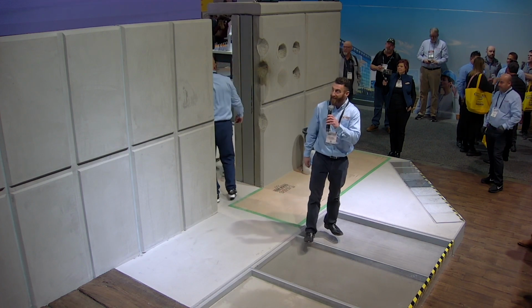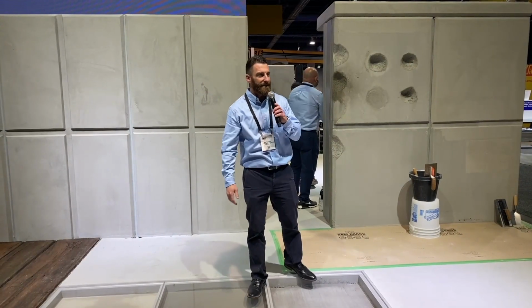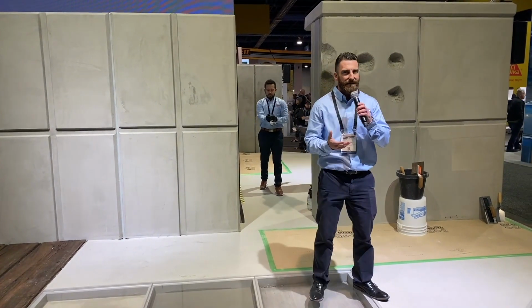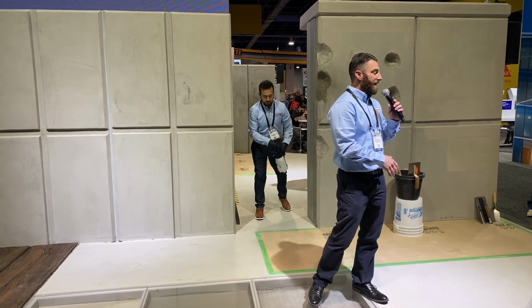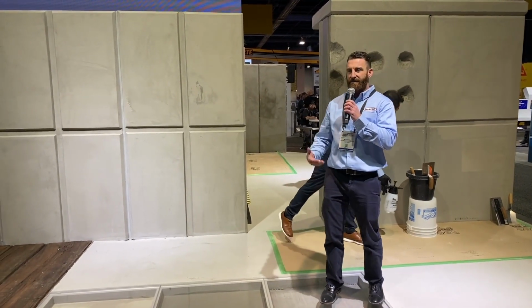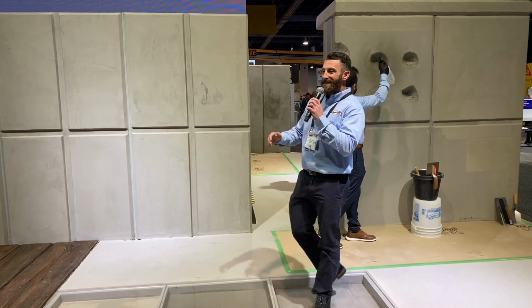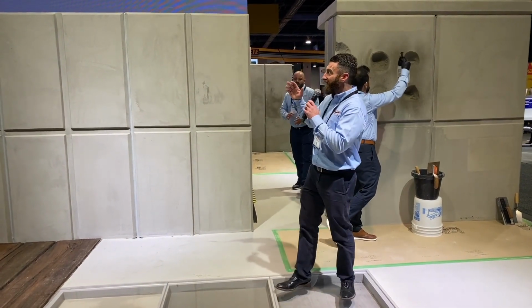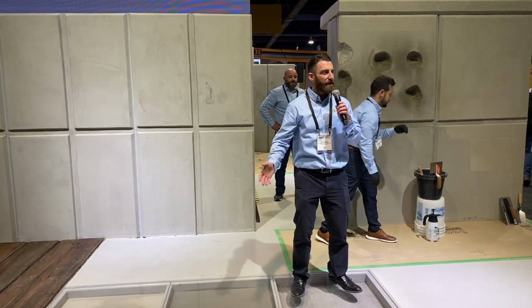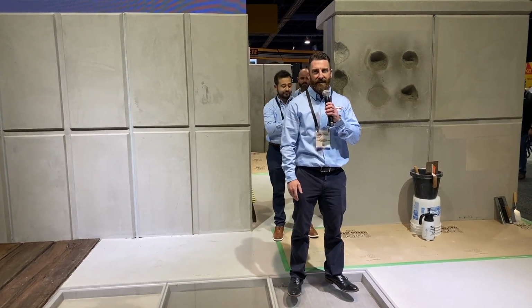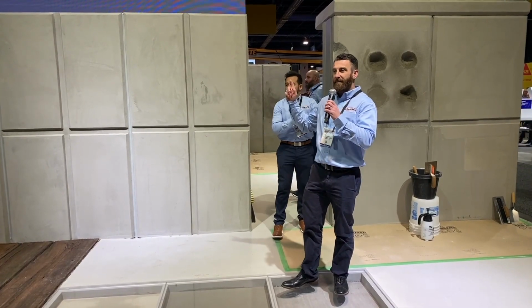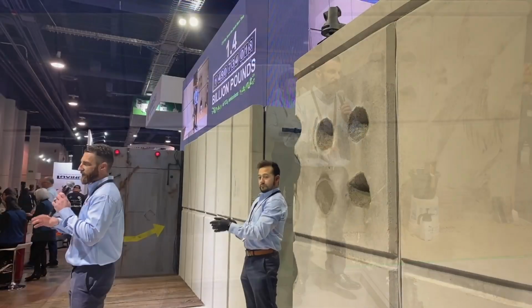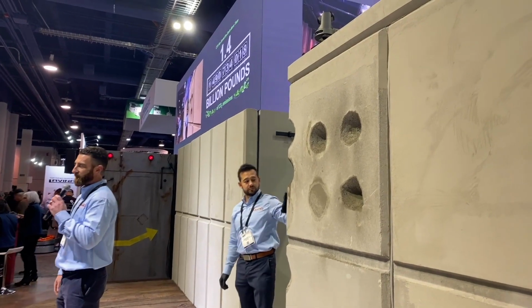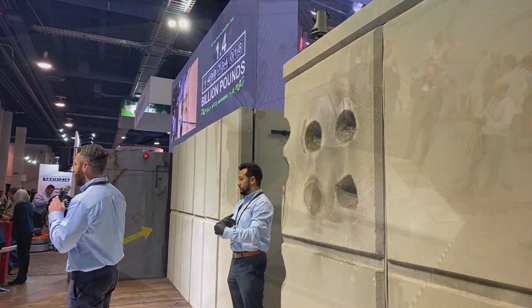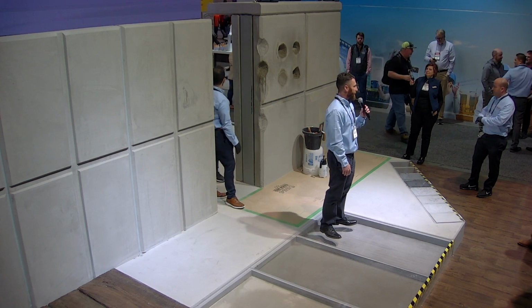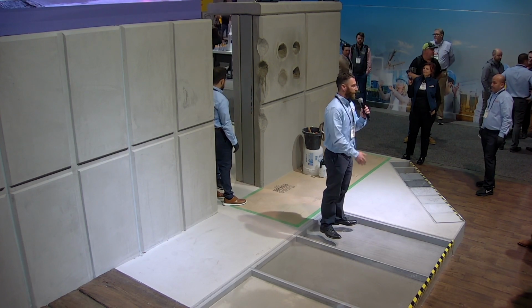Now, we've recently completed environmental product declarations, or EPDs, and showed that the global warming potential for our cement is actually about 25% lower than a traditional Portland cement. So that means CTS Cement has actually saved the Earth almost 1.4 billion pounds of carbon emissions by replacing Portland cement with RapidSet cement. And these are real numbers. These come directly from the Environmental Product Declaration, which is a certified official accounting of CO2 emissions. Plus, we're doing that without having to dilute our cement with inert fillers like limestone. So we're very proud to do our part to reduce global carbon emissions.